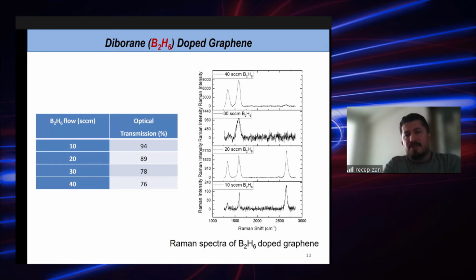Let me move to diborane doped graphene. Initially, we tried to follow the synthesis procedure by changing the diborane flow rate. So we tried 10, 20, 30 SCCM. Then we tried to adjust the growth time. During this, our initial characterization was Raman spectroscopy as well. As you see, as we increase the flow of diborane, we lose the graphene structure in terms of homogeneity and thickness. Particularly 30 SCCM or 40 SCCM provided us with a graphite structure. I mean, a very thick structure.